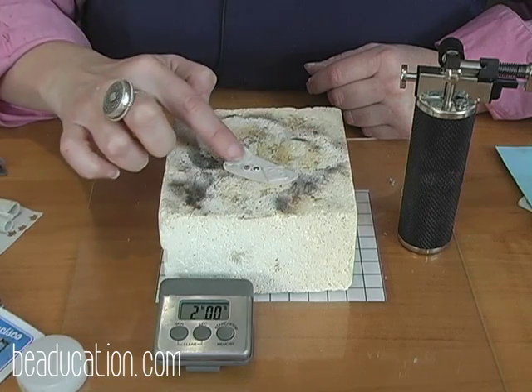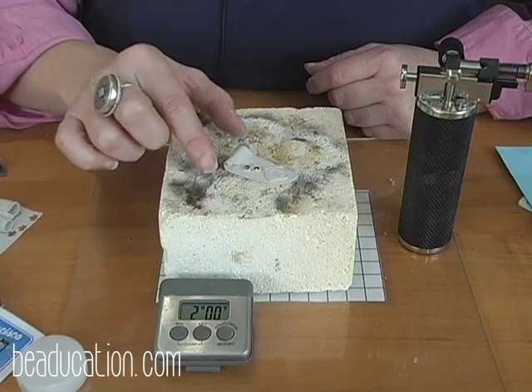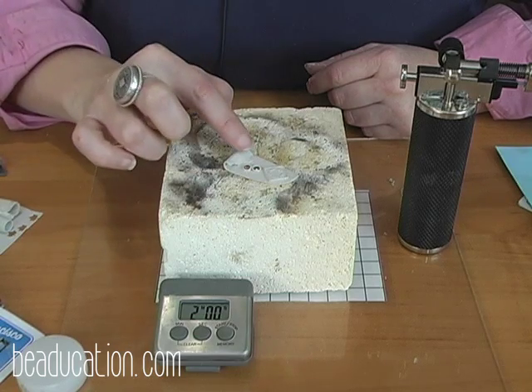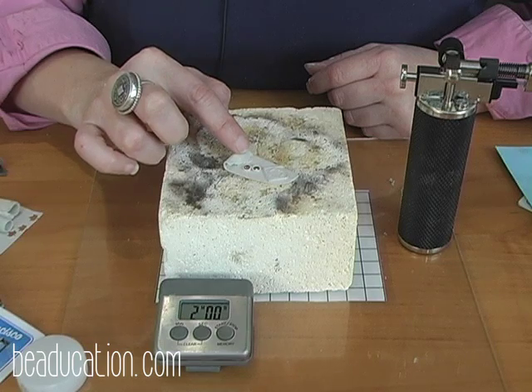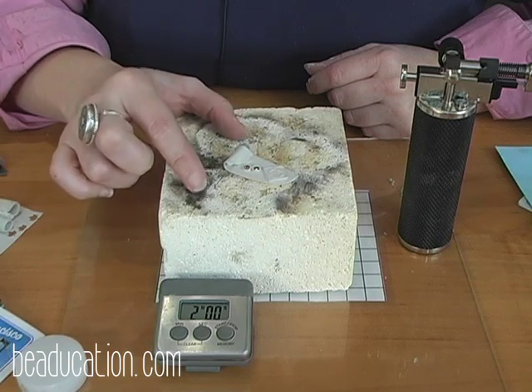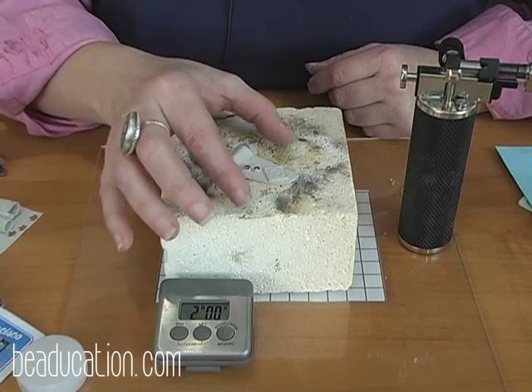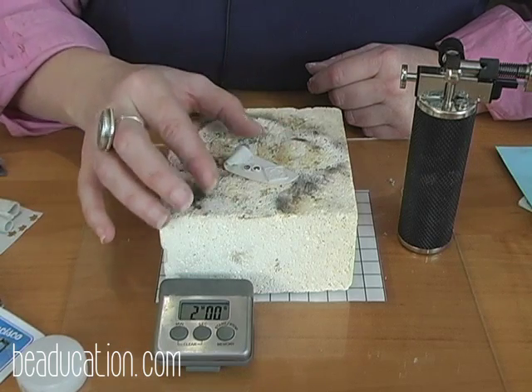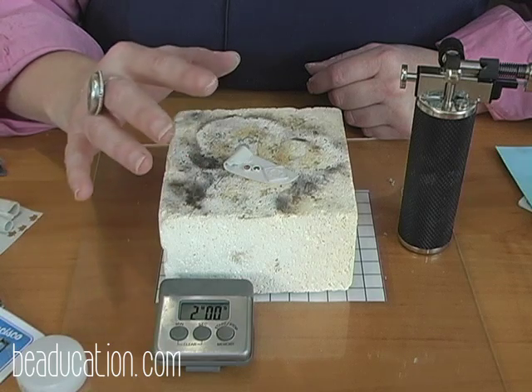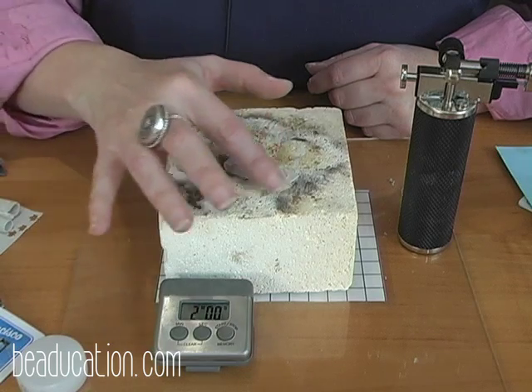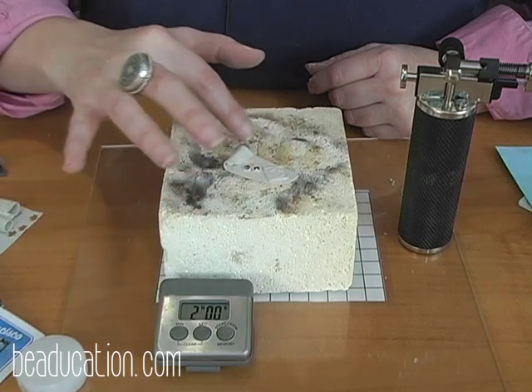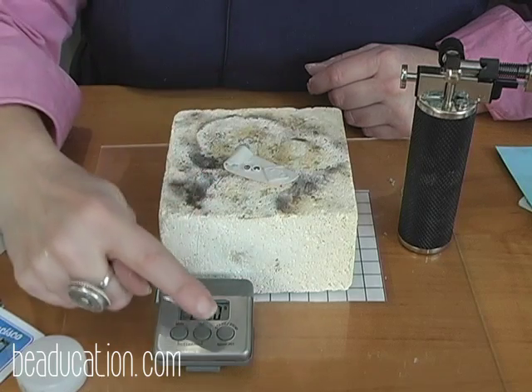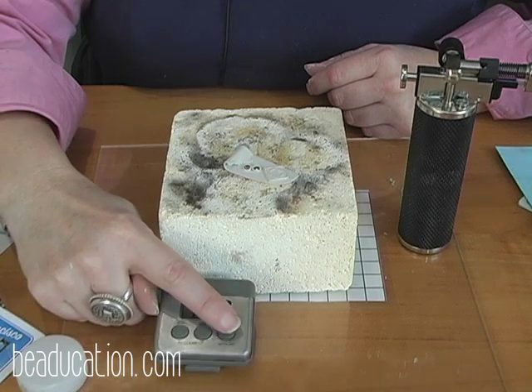You're going to actually see the PMC piece start to flame. That's the binder burning away from the clay. And during that flaming portion is when the piece actually shrinks. Once the flames have stopped, we're going to continue with the torch, bring this piece up to a dull red glow, and that's when I start my timer.